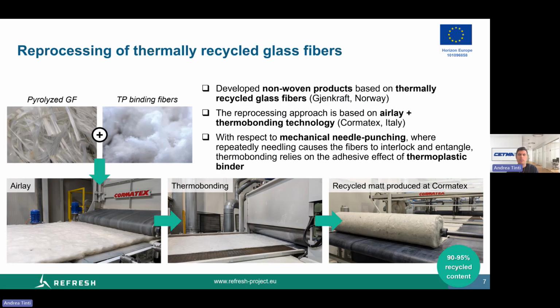First of all, non-woven products, a non-woven mat in particular, was developed based on thermally recycled glass fibers. The processing approach was based on a thermobonding technology, thanks to the collaboration with the Italian company Cormatex. With respect to traditional needle punching, thermobonding relies on the adhesive effect of a thermoplastic binder. So this can help when using recycled fibers, where the thermal treatment at high temperature could have caused material embrittlement.